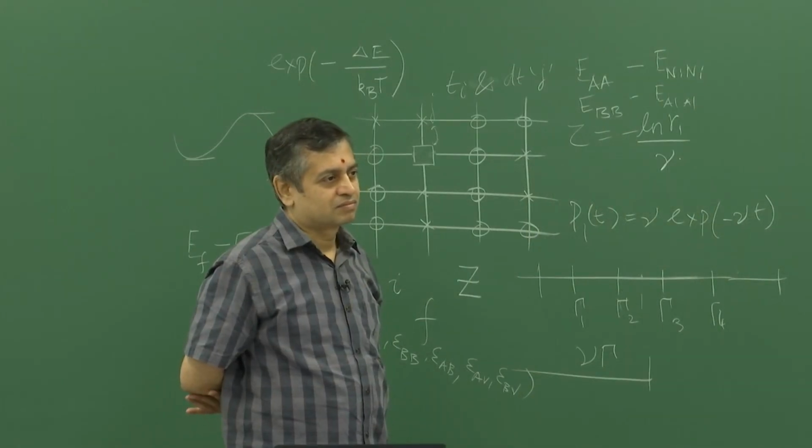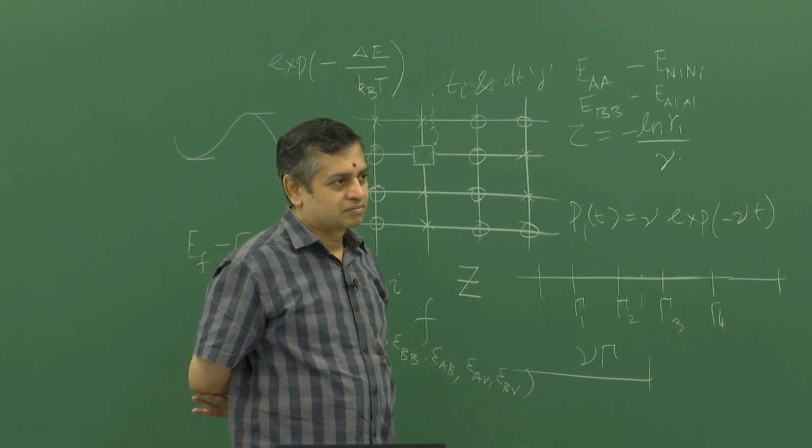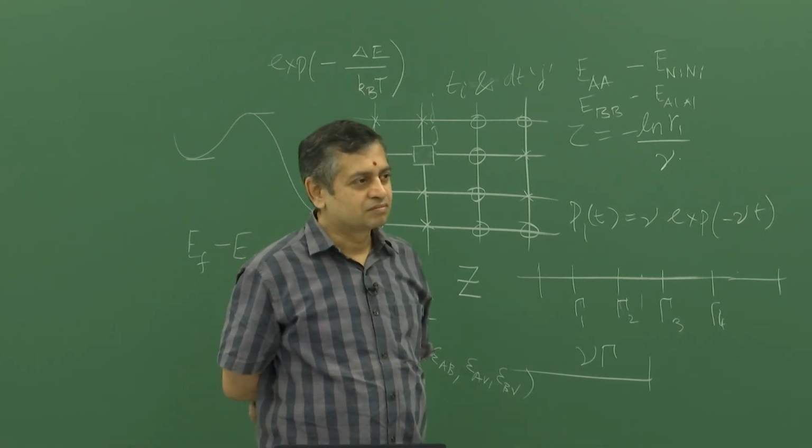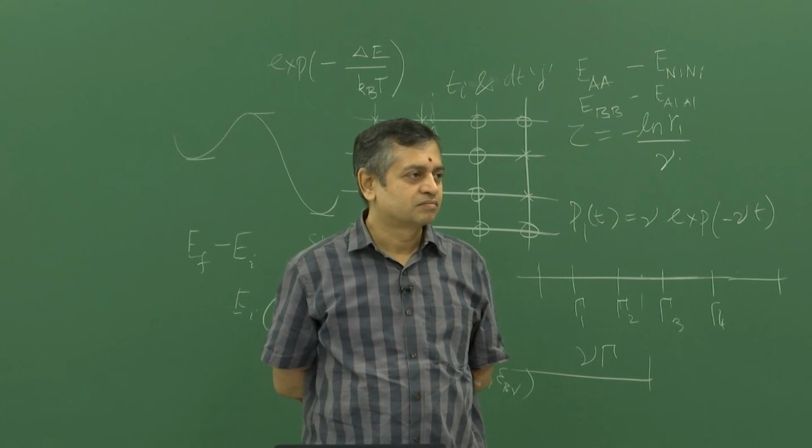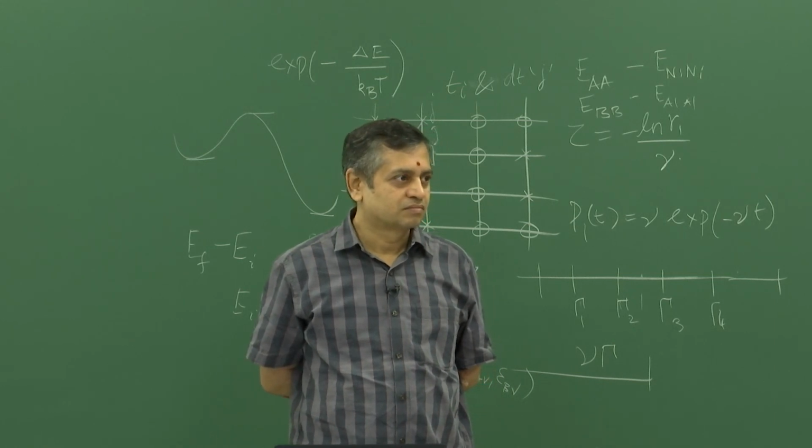So here you have four possibilities. You sum up all these four possibilities, the probabilities of these four changes, take the inverse, and then you have the average time step. The mistake you make is, as far as I remember, very small. So in principle you can save the time for the second random number, which costs quite some time. If you make a million steps, you can save this time and do a few more steps instead.